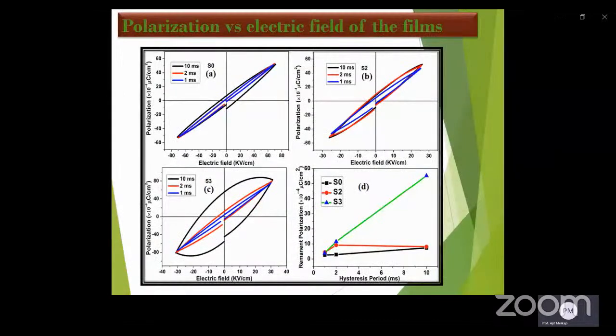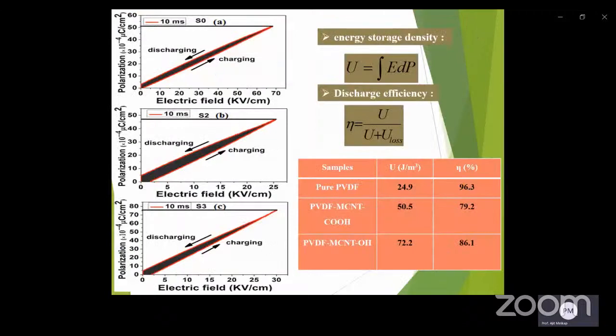The variation of polarization with electric field has been shown for different samples at different hysteresis period. We observe periodic electric hysteresis loop for S0, S2, and S3 except S1 and S4. The increment of remnant polarization with hysteresis period for S0, S2, and S3 has been observed. This is because with increasing time, more dipoles are able to orient in the applied field direction.